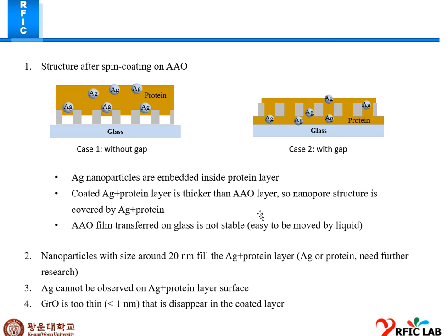If we put the Ag particles, the Ag will cover all the content, and the nanoparticle size is 20 nanometers, filling the Ag protein layer. Ag cannot be observed on the complex layer surface. As I already said, the graphene oxide flakes are larger than the Ag protein complex. The Ag nanoparticle is quite a bit smaller than the graphene oxide. In the case without gapping, the graphene oxide acts like a barrier, so that is why it does not penetrate into the AAO pore and stays on the pore surface.